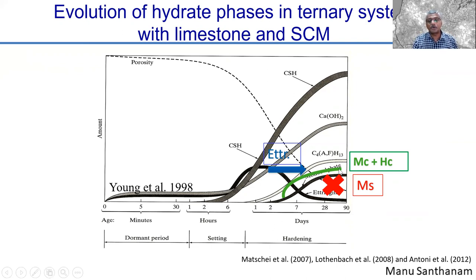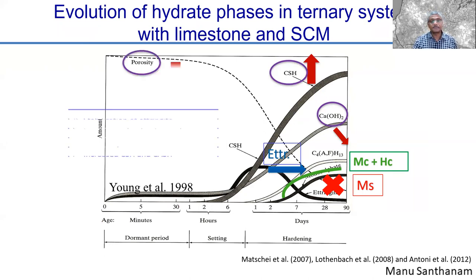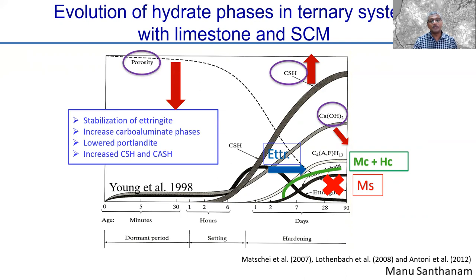So that's an additional product that you're forming. And in the long term, you're also reducing your portlandite content and converting this to additional calcium silicate hydrate. So overall, what you're resulting in is more CSH in your system. That means more binding characteristics, smaller porosity, and as a result, you get better results as far as durability is concerned. Okay, so porosity also goes down.